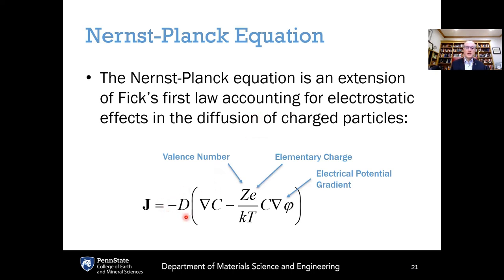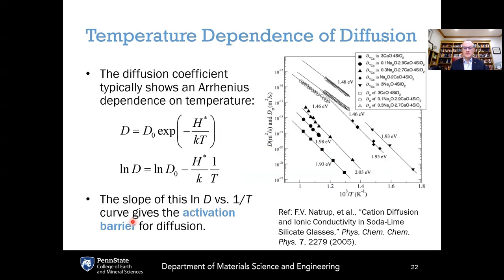You can see the first part of the equation here is the same as Fick's first law, but then there is another driving force. So you've got the concentration profile driving force, and then another driving force, which is due to the electrostatic interactions between the electrical potential gradient and the charge of the species that is diffusing. And when you sum up those two driving forces, that gives you the total driving force multiplied by the kinetic coefficient here, D, and then that will give you the total flux accounting for both driving forces.